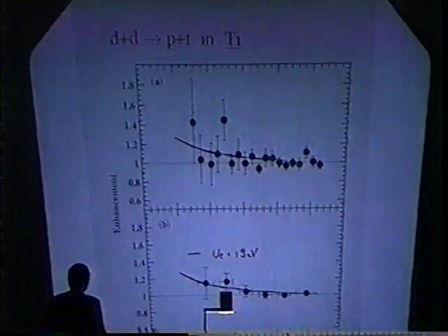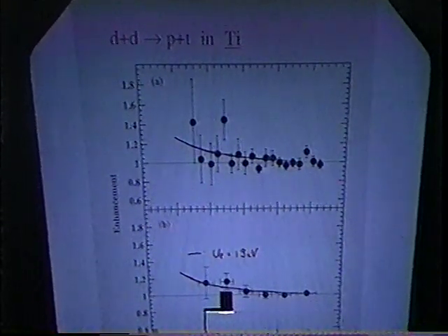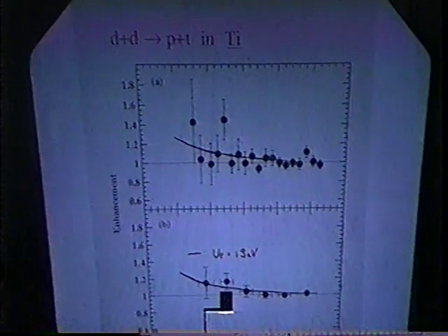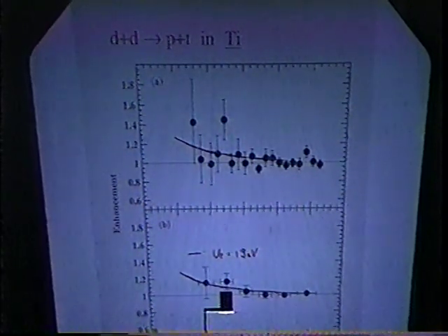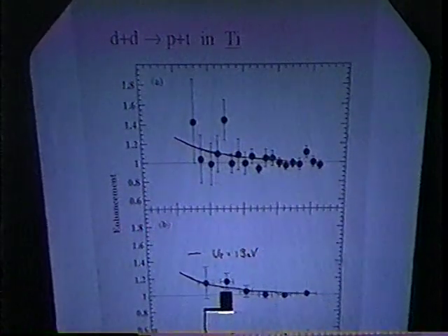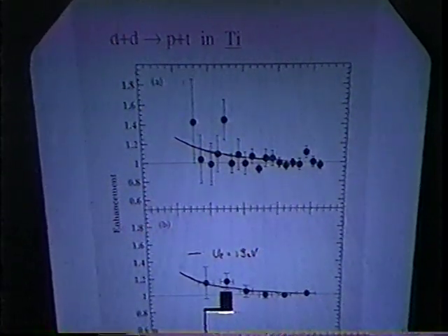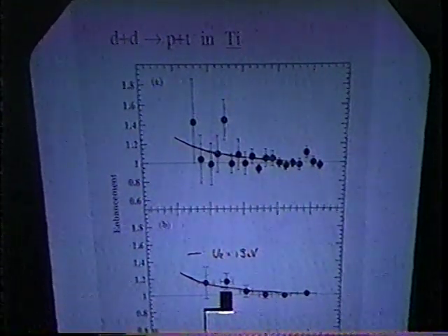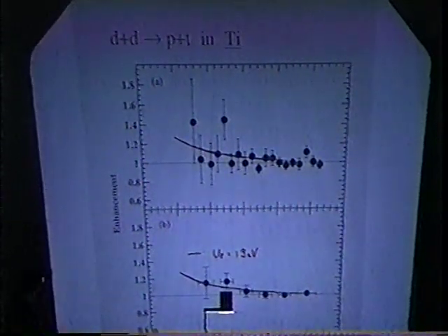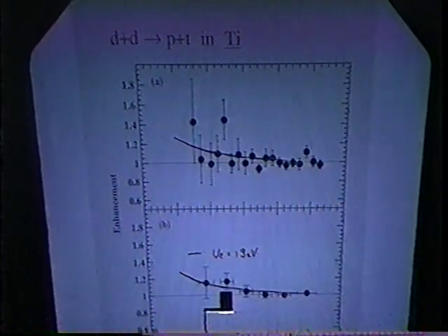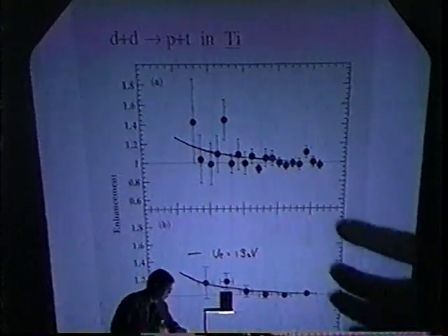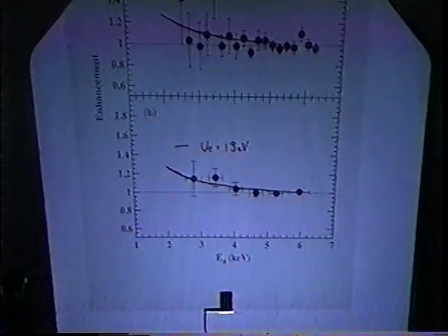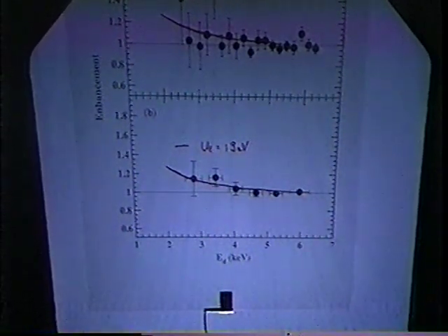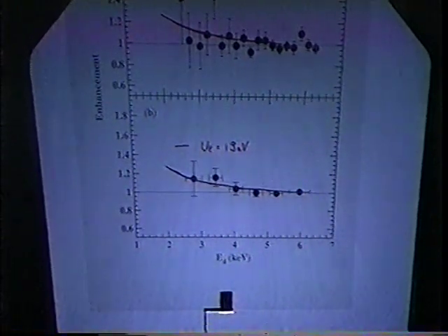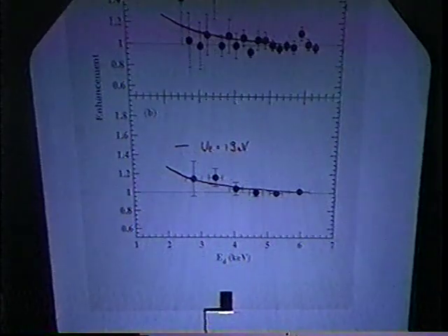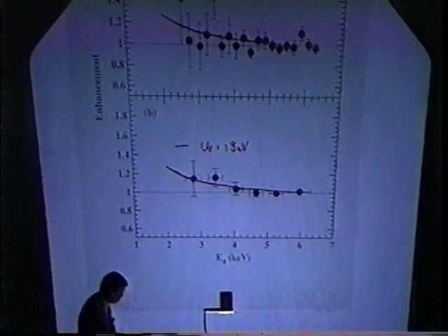So the upper part is just a raw data, we call it the enhancement because we could expect the enhancement for the electronic screening. But actually the statistics not so good, so the data is fluctuated. In order to get the better statistics, we just averaged each 3 points and get the lower figure. Here, we clearly see the enhancement of reaction rate below 4 keV, although the enhancement is not so great. I mean, just only something around 10% enhancement.